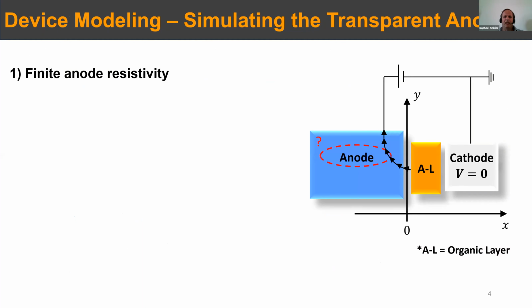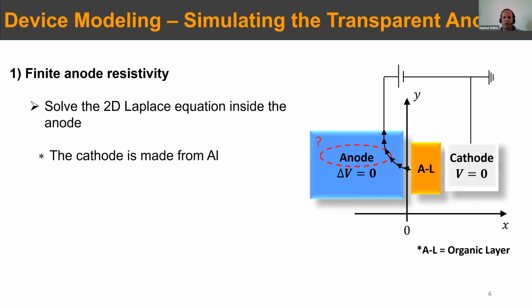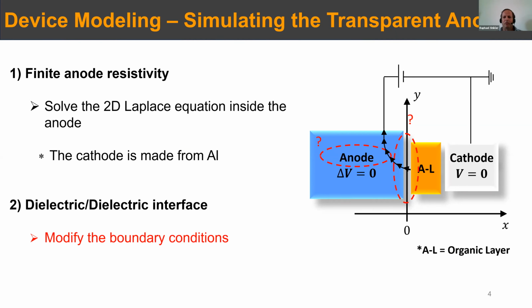The first one was how to simulate a transparent anode. The idea is that we solve the two-dimensional Laplace equation inside the anode. The cathode in our case was made of aluminum, so there was no issue in trying to solve anything there because we can assume that the voltage there is constant. Then we need to couple what we have in the anode, which is one dielectric, to what we have in the active layer, which is a different dielectric, and therefore we have to modify the boundary conditions at the solar cells.